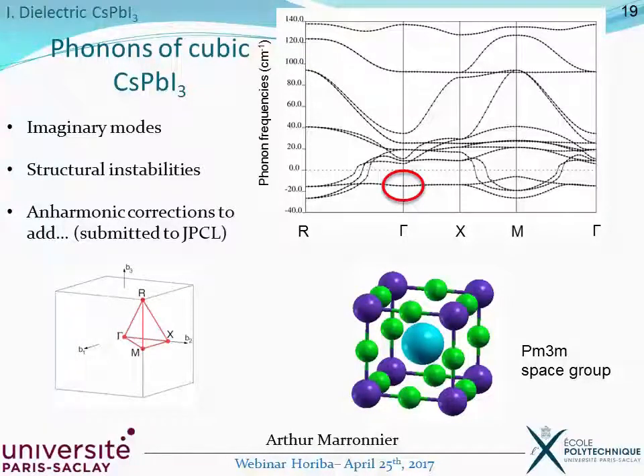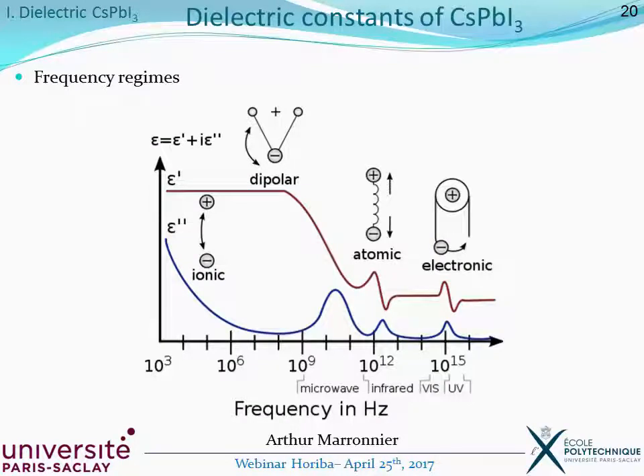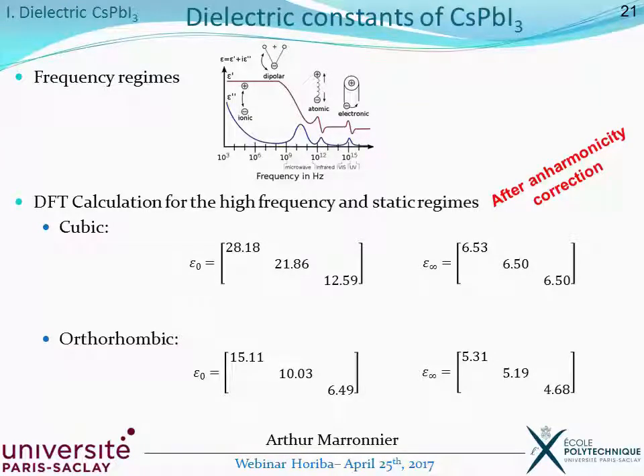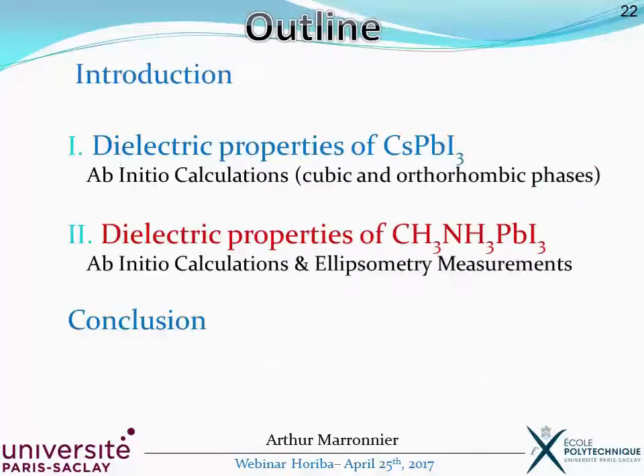Well, if we take into account these anharmonic corrections, and we look at both the high frequency and low frequency regimes, here are the results we obtained. In the cubic structure, we have here the values of epsilon at high frequency, and more interesting are the values at low frequency. In the static regime, you can see that we reach almost 30 for epsilon. And for the orthorhombic case, it's a little lower. But what is important is that we've shown that cesium lead iodide perovskite has a high value of epsilon, which is coherent with its inorganic nature. But now what about the hybrid case, the methylammonium perovskite?